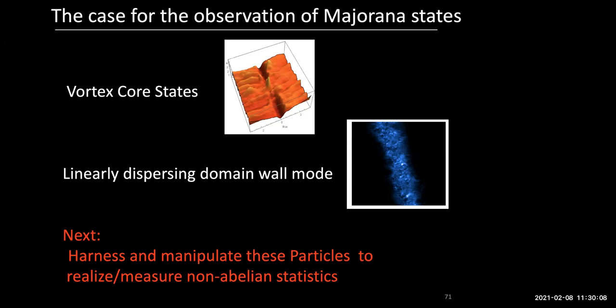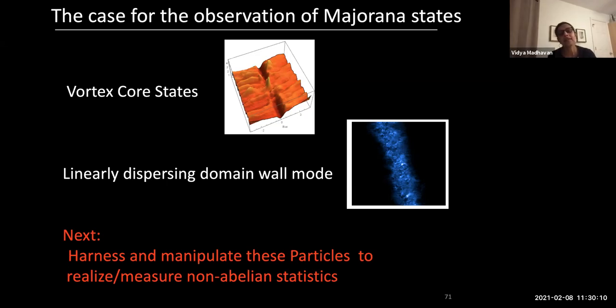now there is mounting evidence that these are indeed Majorana states, both these bound states and these propagating states. I would say that the latest vortex core studies done by Hanaguri's group, as well as Hongding and Hongjun Gao's group, are pretty convincing. The fact that they see states localized exactly at zero bias, and the fact that they see integer spacing, I think that's pretty amazing.